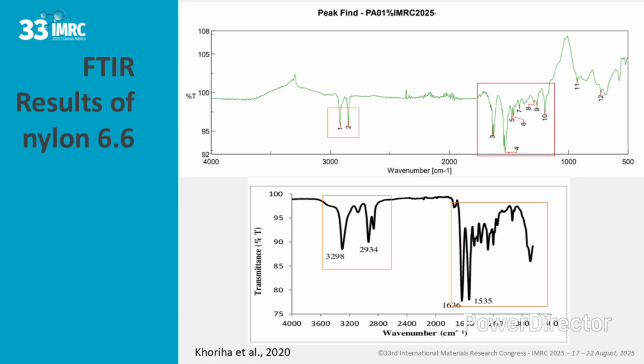FTIR results of nylon. The slide shows 2 FTIR, Fourier transform infrared spectroscopy, spectra of nylon 6.6. Top, green spectrum: corresponds to the nylon 6.6 material used experimentally in this project. Several absorption bands are observed, with assignments in the characteristic regions. N-H stretching signals appear between 3300 and 3200 cm⁻¹. Aliphatic C-H stretching modes are distinguished between 2930 and 2850 cm⁻¹.